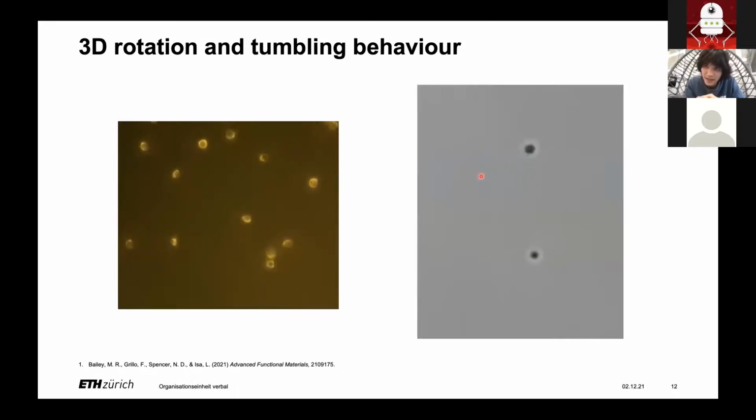And what we expect to be occurring is that because we're using nanoparticles, and again, they have this asymmetry, you've got large chunks of titania dotted around, they have a much stronger angular velocity component compared to traditional thin film systems, which are deposited. So the combination of the thermal fluctuations plus this active angular velocity, we think are in competition essentially between that and the sliding state, which means that on occasion, the particle will leave the plane because it's got a much stronger driving force to do so.